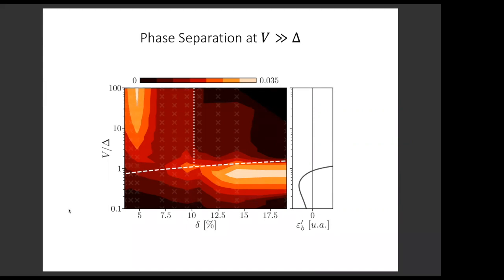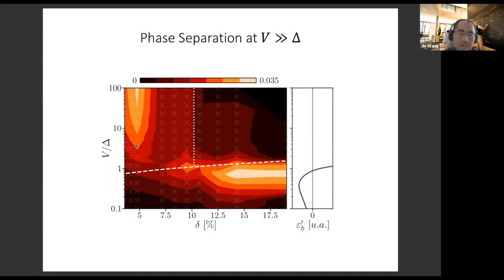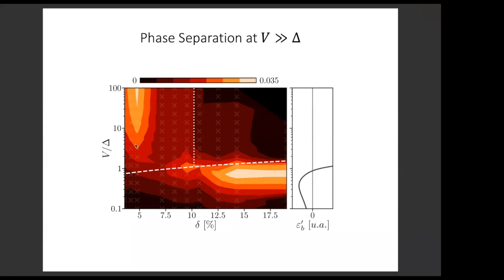So even with this model, at a very large interaction strength V, the low energy theory also becomes strongly interacting. So there's, I think, a lot of interesting stuff there, as a function of doping, which we are still exploring. But the analytical results are valid at the low doping and at intermediate V over delta. And in that region, we already obtained strong coupling superconductivity with Tc over TF up to about 10%. Next slide.